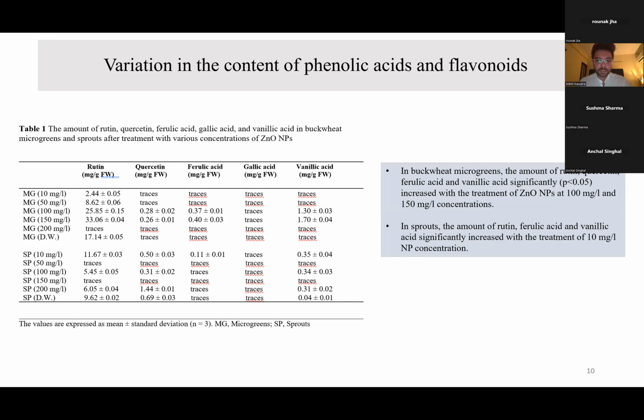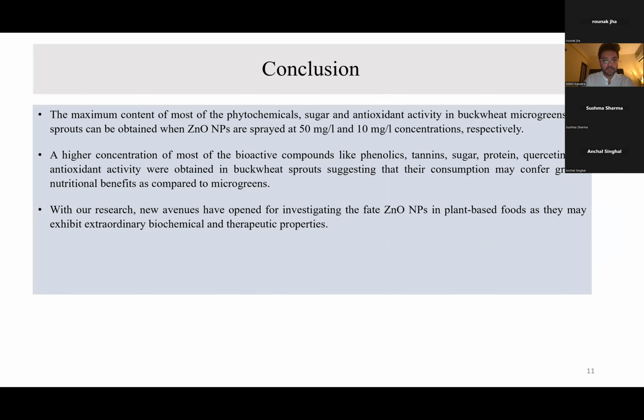Talking about sprouts, the content of rutin, ferulic acid, and vanillic acid significantly increased with the treatment of 10 mg per liter nanoparticle concentrations. Coming to the conclusion, the maximum content of most of the phytochemicals, sugar content, and antioxidant activity in buckwheat microgreens and sprouts can be obtained when nanoparticles were sprayed at 50 mg per liter and 10 mg per liter. So for microgreens, the optimum concentration of nanoparticles was 50 mg per liter, whereas for sprouts, it was 10 mg per liter.